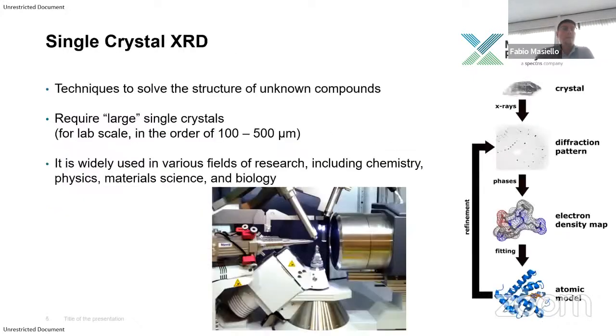So, starting with single crystal XRD, that's a technique used to solve the structure of unknown compounds. It requires large crystals, and what is large? For lab scale it is in the order of 100 to 500 micron. It can be smaller for synchrotron, for larger scale facilities, but still rather large crystals typically. And you see on the right side of the presentation, you have your crystal, you impinge it with X-rays, you get a diffraction pattern, and then in your structure solution, you will try to fit some phase and refine it until you get the atomic model that best explains your diffraction pattern.